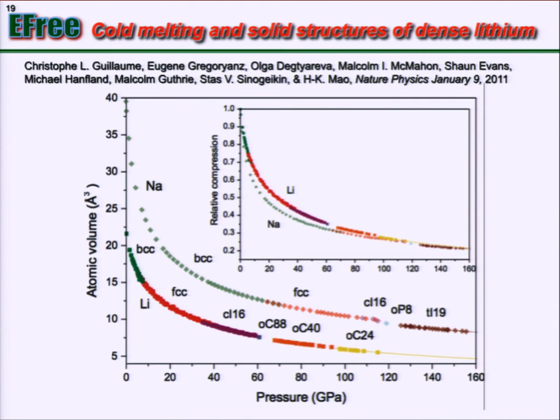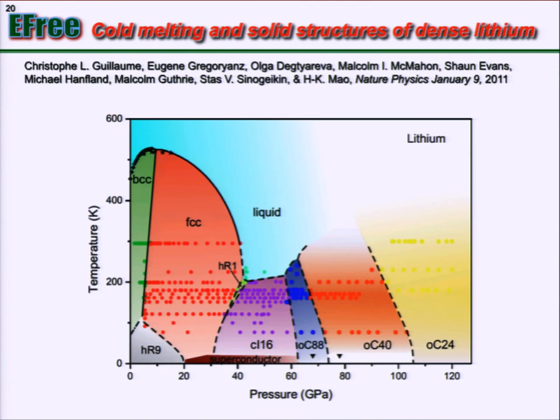Lithium is smaller than sodium. Actually, it has the same structure transition as sodium, and you can see that in almost the same pressure and volume range, they have the same structure, like a BCC here, FCC here, and they all become cI16. So we determined the phase diagram of lithium.